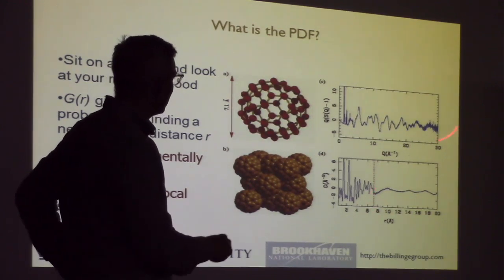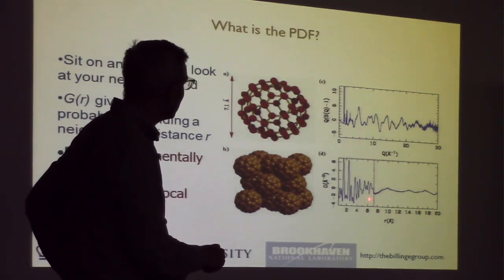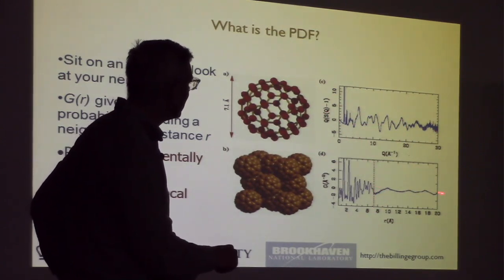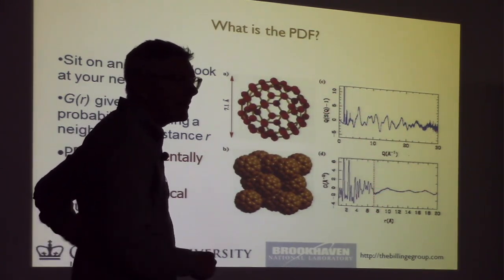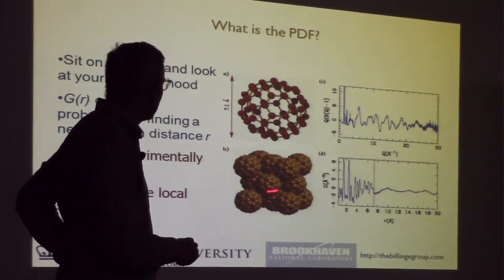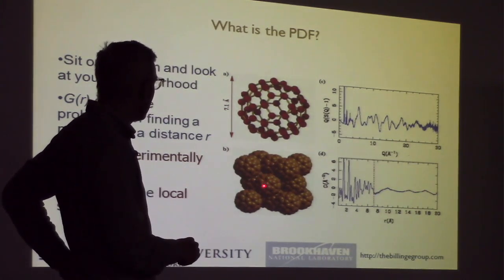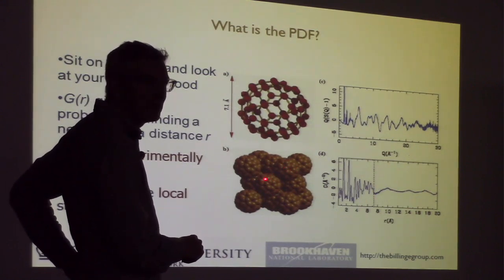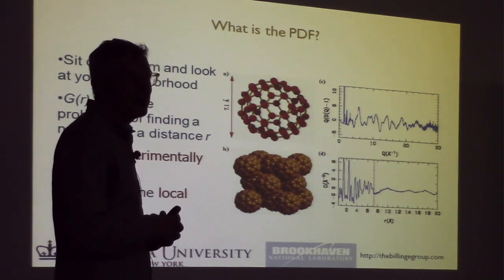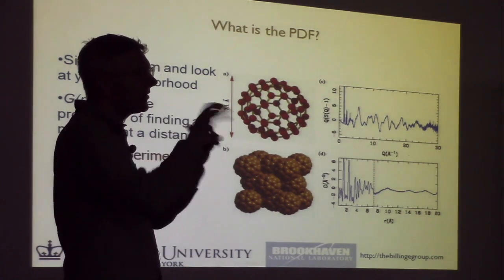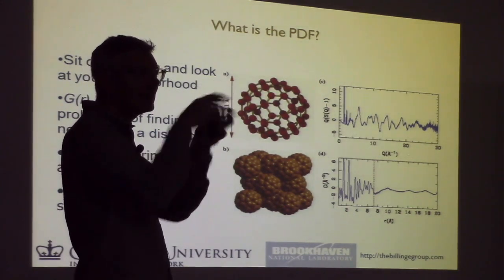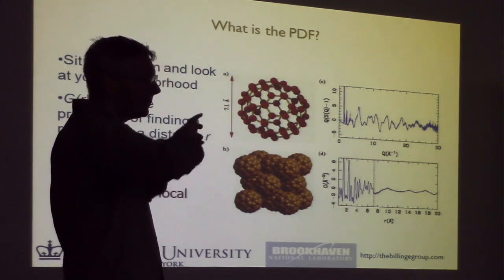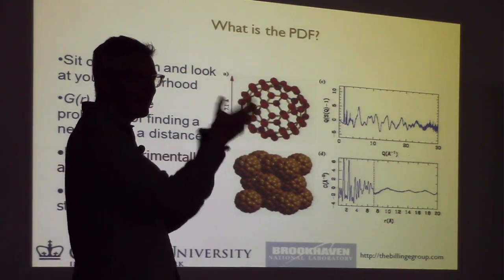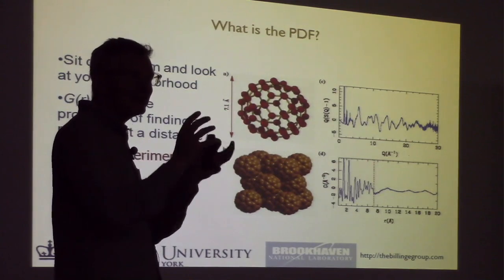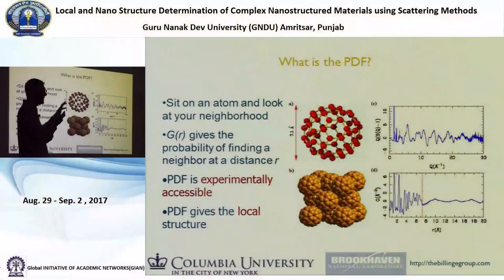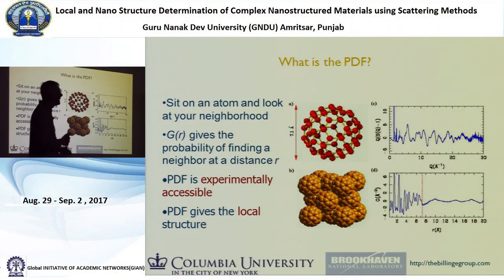And then the PDF, which is just the Fourier transform of this data here, has essentially no signal out here. So why is there no signal there? It's because I'm sitting on an atom on this buckyball, and I'm looking at an atom on that buckyball. And the data were collected at room temperature, and at room temperature, the C60 balls are dynamically reorienting. They're spinning like this at room temperature. And this smears out all of the atomic density on the surface of the balls on average. So the time average view of that is a smooth, hollow sphere of carbon.